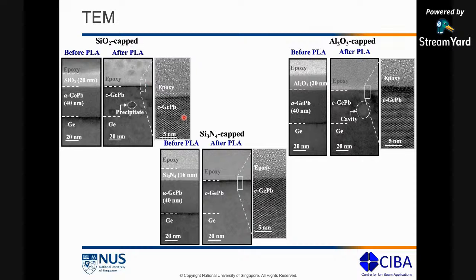The silicon oxide and silicon nitride, the lead substitutional behavior was much better. So you can see from the lattice, from the TEM image here. Compare that to the aluminum oxide. We had all these development of cavities in the germanium lead layer after the pulse laser annealing step, right? So that kind of matches with what we got from the high resolution RBS measurements as well, right?